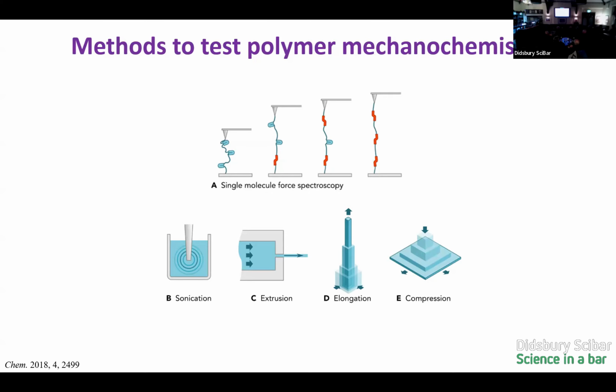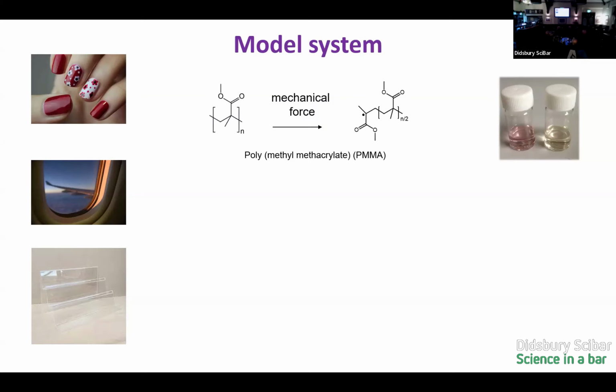And when we pull on these acrylates, we don't have a mechanophore in them at this point. We break the bond in the center of the polymer chain, and we can follow that by adding a dye that changes color. So we can go from pink to yellow in this case, and we can follow it quantitatively using spectroscopy. So we can measure the absorbance of the solution and see how many of our bonds have broken, or we can measure the length of the polymer chains that we get out at the end. So that's what we do. And what we see is when we look at sonication, this is the process that is going on.